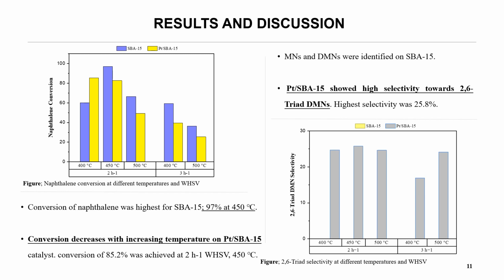Furthermore, although methylnaphthalenes and dimethylnaphthalenes were not identified in methylation products on SBA-15 catalysts, in contrast, PT-SBA-15 showed significant selectivity for 2,6-dimethylnaphthalene isomers across all temperatures tested. The highest selectivity of 25.8% was achieved at 450 degrees Celsius and a space velocity of 2 per hour.